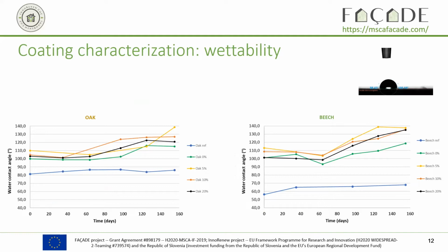So on the top right, you can see a drop of water deposited on the surface. And we are measuring the angle that the drop makes with the surface. So the lower the angle, the more hydrophilic the surface is, the more the water can be absorbed by the surface. You have the results here for oak and beech, and these results that you see now,